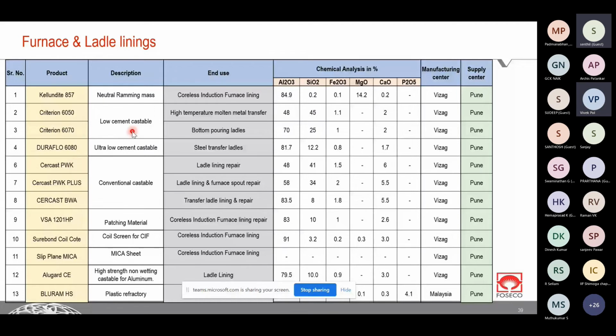So the low cement castable range, then conventional and ultra low cement for patching. We have seen this. Then for coil coating, we have a material which has very high alumina and again is a very good product. Mica sheet again is from a safety point of view. Then something for aluminium we will not discuss here, and Bluram HS is the only material which is not made in India, but from an availability point of view, we can assure you that the material will always be available.